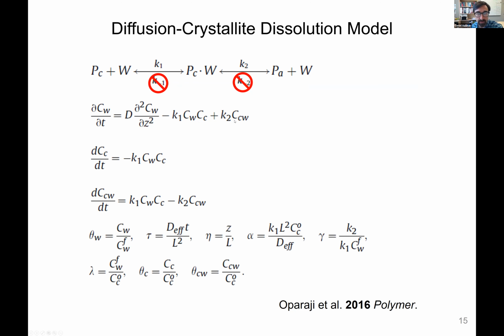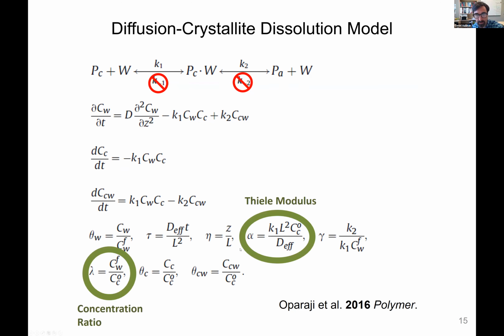And if we non-dimensionalize this, you actually get quite a few dimensionless variables and parameters, but I just want to focus on two: this Thiele modulus, which is just competition between diffusion and reaction, and a concentration ratio, this lambda, which is the ratio between the final water concentration and the initial water concentration.